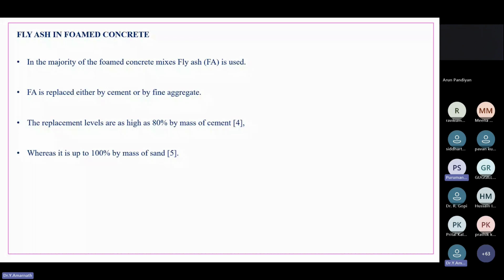For the same density, we can replace cement with fly ash, and the replacement levels are as high as 80% by mass of cement in foam concrete production. Whereas it is up to 100% for sand, as sometimes we need not use any sand content to produce foam concrete. That's the reason why 100% fly ash can be used. Only cement, fly ash, and foam can be used to produce foam concrete.